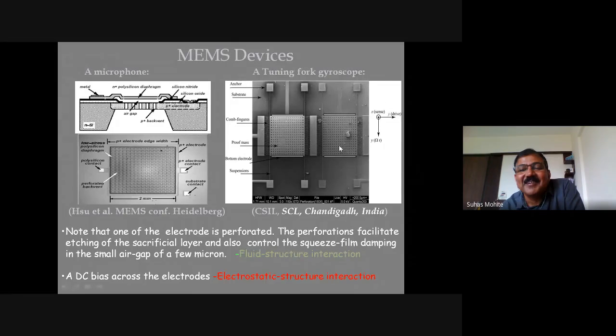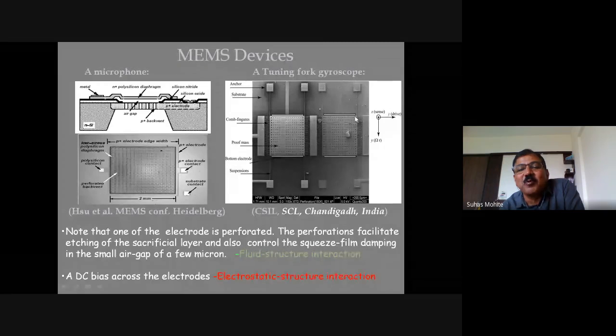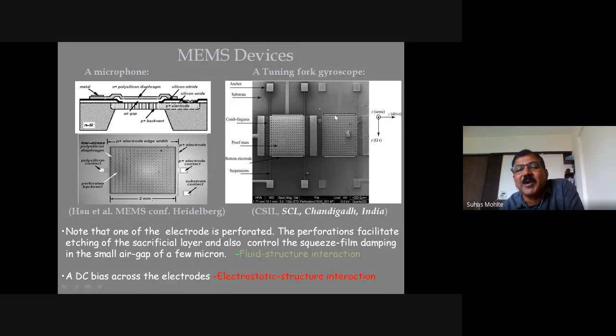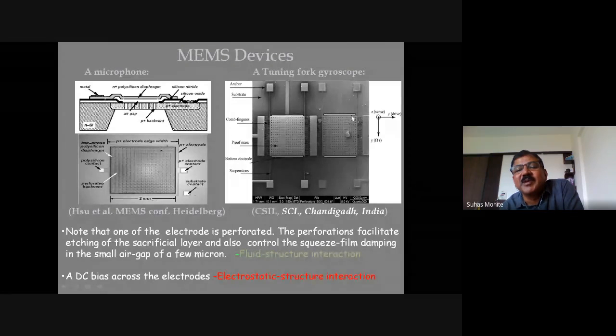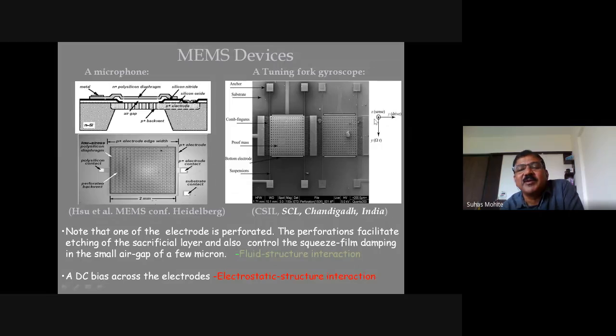It takes a while. Your hair is pretty big. Here is 100 micron. So 400 micron means this particular length of the plate is equal to the thickness of 4 hairs. 4 hairs put one beside another, the thickness will be as that of this particular plate. And the gap between this plate and the substrate underneath is only 1 or 2 micron, which is 1/100th of the thickness of hair.